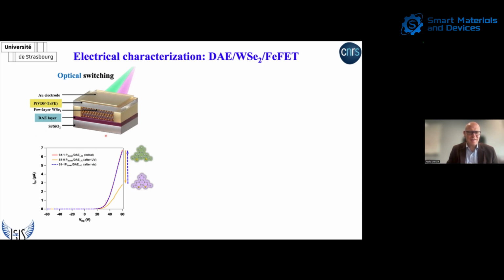And so we tested the optical switchability, say the possibility of using light at different wavelengths to change the electrical characteristic of the device. You can see here we can change about 60% the current through a junction by irradiation with UV and visible light. So UV, we close the diarylethene, and visible, we reopen the diarylethene. And this allows a very reversible modulation of the current through the junction.